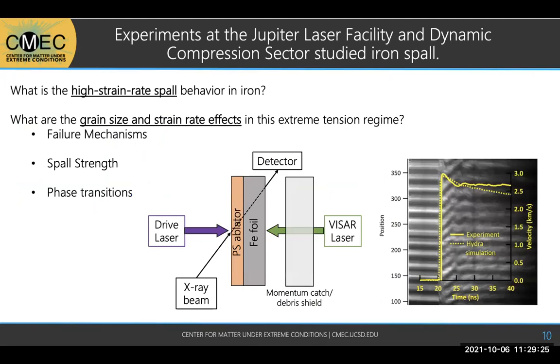All right, so now I'm gonna start discussing my results, and I might need to move a little bit faster, but I've essentially performed experiments both at the Jupiter Laser Facility and the dynamic compression sector to study iron spall. And you can see my main questions that I've been investigating, where my three main points are the failure mechanisms, the spall strength, and phase transitions. So we had really thin iron foils of varying thickness depending on the laser facility.